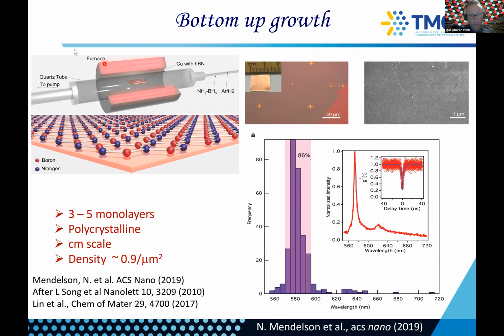The other thing is that we tried actually a bit of STM with a few collaborators, and personally, we never even managed to get an image. So hBN is insulating, so we could never get a proper image. The most challenging part was always contamination, because when we transferred the hBN to the substrate that they wanted, like HOPG or something conductive, we would always have a lot of contamination, and we couldn't really solve it. And so we just, how should I say, dropped the ball and stopped.